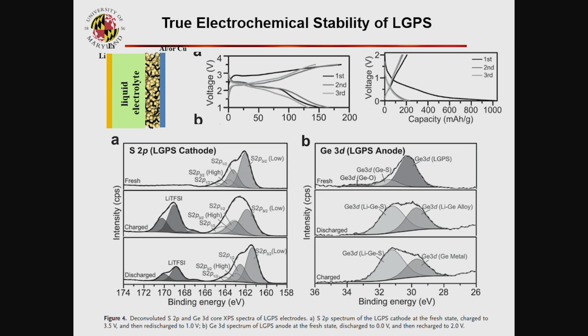How can you confirm the reaction is really true like we expected? So measure the sulfur or measure germanium when they change the germanium sulfide to germanium lithium compound and alloy, the germanium valence was really changed. So we confirm this is really a reaction with the conversion reaction followed alloy reaction. And this is the same as lithium sulfide. And this is, we use the organic electrolyte to test.